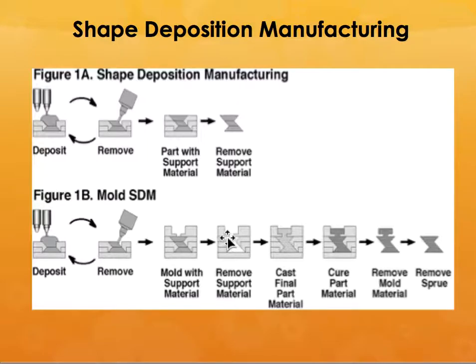So by combining the deposition with the machining, with an addition step and a partial subtraction step, you then deposit a ceramic gel casting slurry into that, and then you remove the wax mold around it. You can machine off the extra material in the green state itself. Then, in the case of ceramics, you have to do binder burnout and sintering, because this slurry contains some binders and things like that.